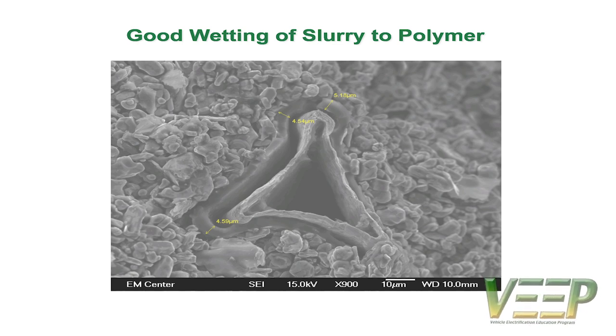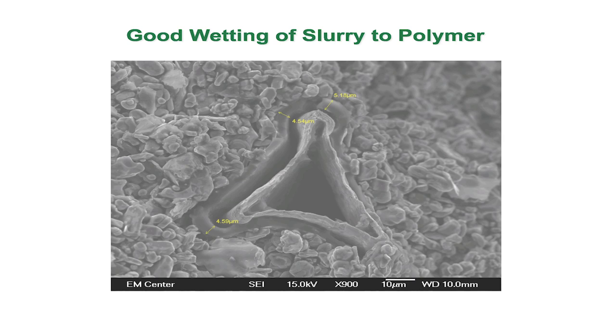And what happened here is we took the whole thing, we froze it in liquid nitrogen and cracked it so we could image it. And we noticed that when we froze it, the polymer pulled away. This is the copper antimonide here. This is the copper foam. Oh, thank you, Cynthia. That helps a lot, thank you. So this is the copper foam. This is the copper antimonide. Remember, it's thicker where you have an edge. And this is the polymer which pulled away.